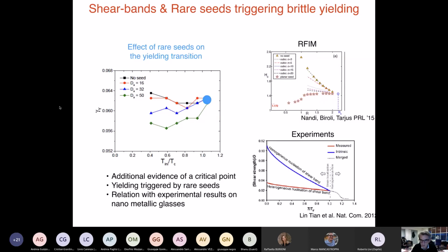And while I will not discuss the figure in detail here, it's really what has been found in the experiments on metallic glasses. Very small systems actually have a value of gamma y which is much larger than larger systems, and this was exactly interpreted in this way in this experiment. For very large systems, which correspond to the red line here, you have heterogeneous, what they call, nucleation. It's not standard nucleation, but there is some region inside the system from which the shear band can form, which corresponds to the rare seed that I just discussed.